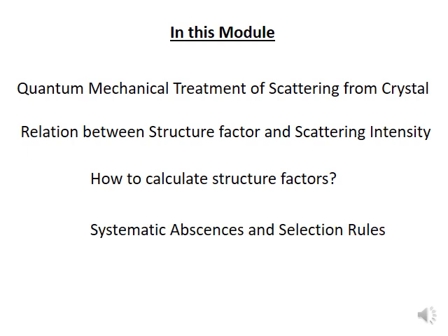From calculation of structure factors, we found out for certain lattice types, scattering from some of the lattice planes, corresponding to the reciprocal lattice vectors, is missing. These are called systematic absences, and that's how you can define selection rules for either presence or absence for certain crystal systems, for X-ray scattering and neutron scattering in general.